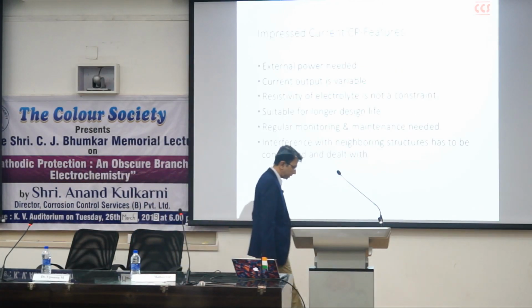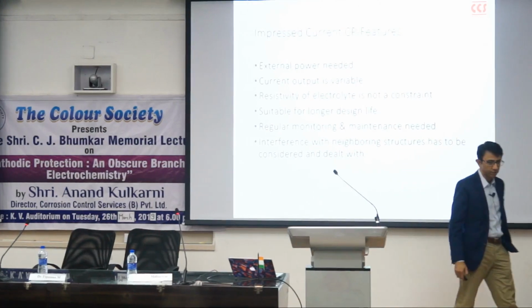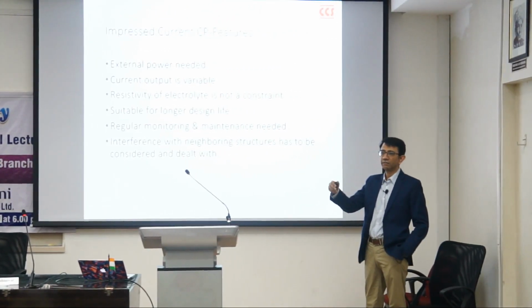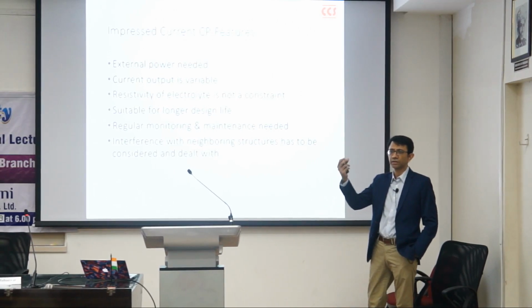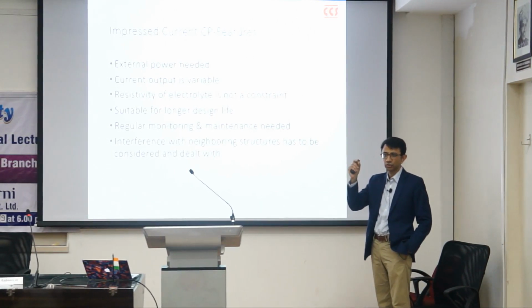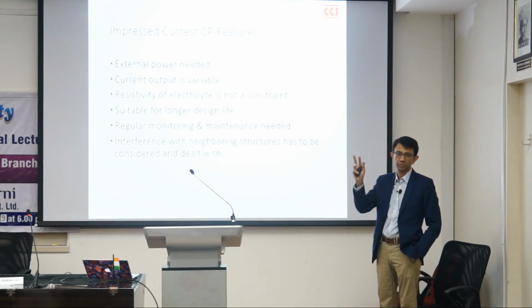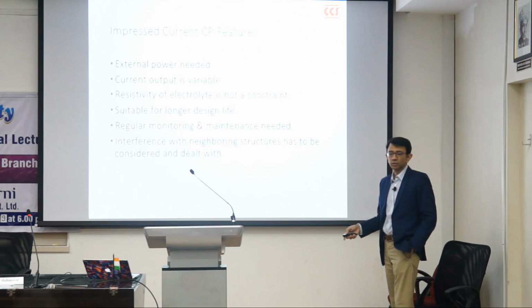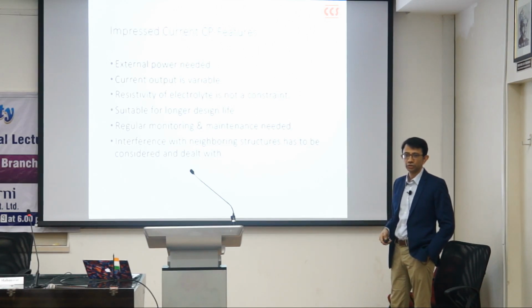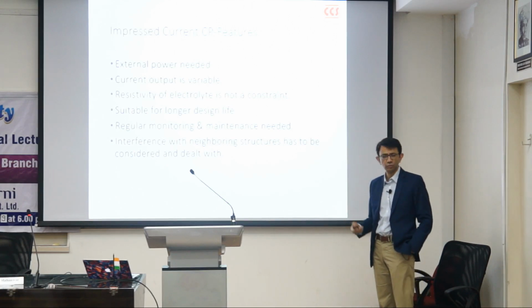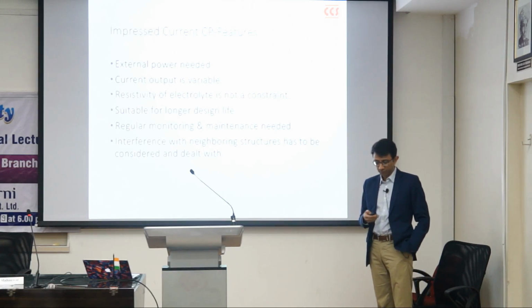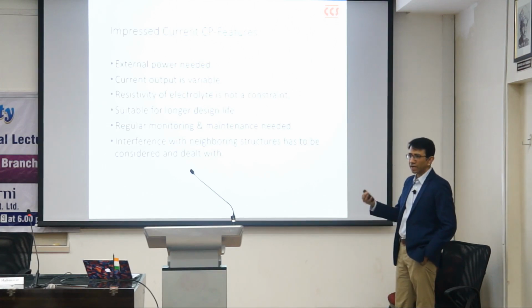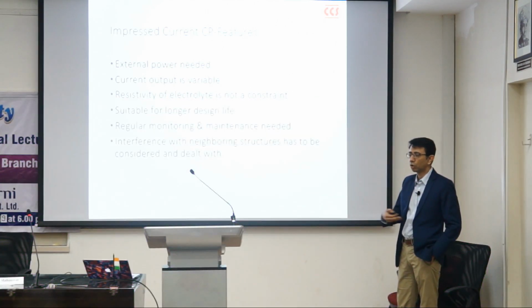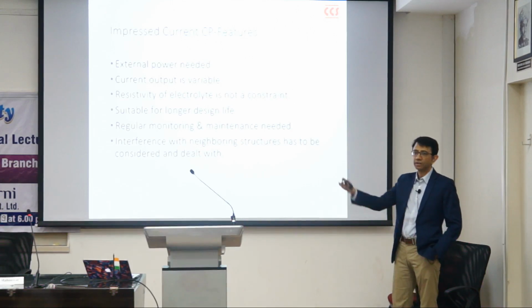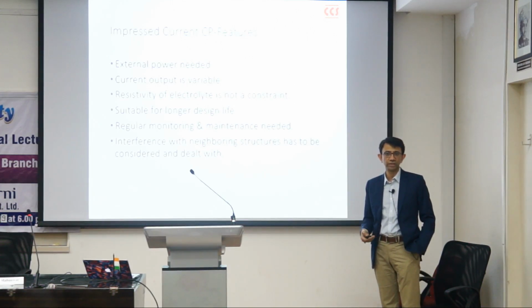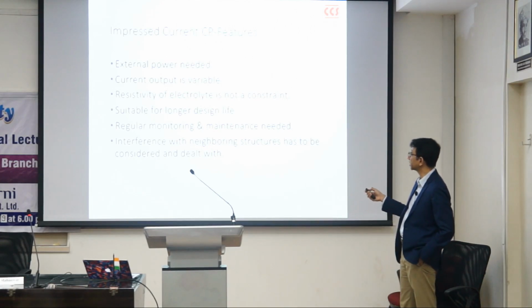So impressed current CP, of course, does away with all the limitations that are imposed by the galvanic system. The galvanic system has very limited power because the power of the galvanic system is the result of the natural difference in the intrinsic potentials of two different metals. That's it. So obviously you have limited power. We looked at the electrochemical potentials of zinc and magnesium, 1.1, 1.5. You have very limited power available to provide protection. So if you have very high resistivities, if you have long design lives, if you have a 200-kilometer long pipeline, it's just not feasible to use galvanic protection. So that is when we use impressed current CP.